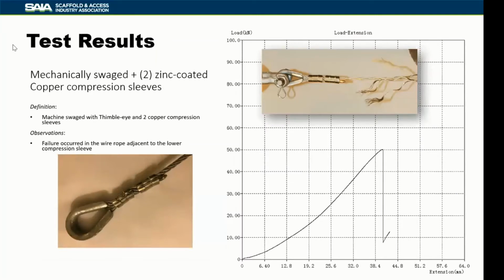If we go to basically the same approach, only with two zinc-coated copper compression sleeves, again, the failure occurred in the wire rope just below the lower compression sleeve. In this particular test, you can see the result that we actually got in the inset picture, where you can see that there were a couple of strands that were not failed, but the majority of the strands all failed. Again, the breaking strength is right in that exact same region of about 11,000 pounds of force. Our extension, again, is pretty close to about 1.5 inches.